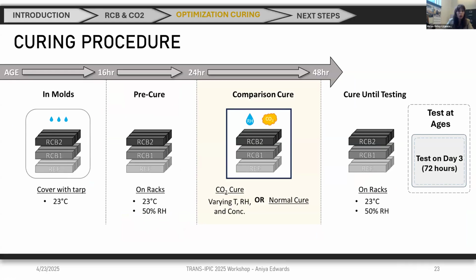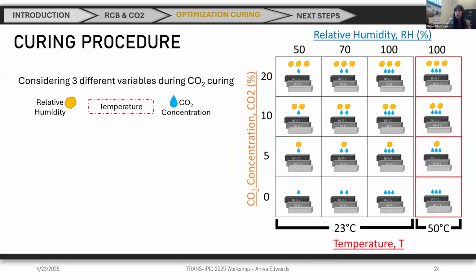Now, we wanted to optimize the process, so we need to check a lot of variables, right? To be able to see all the potential case scenarios and then get a model to give us the response we want, which is what are the best conditions. So for that, we cured all the samples in the same conditions, except for a small period of time where we will change humidity, temperature, and percentage of CO2. So in total, we will have 16 different curing conditions that we will test, and 9 samples per curing condition, 3 per different mix. Therefore, we are talking about a total of 144 samples, 48 per mixture. And then we will test them at 3 days to see how it affects the early age properties, especially compressive strength.